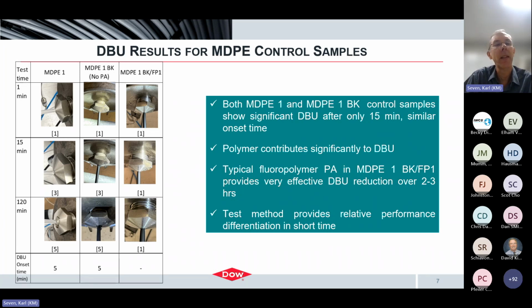MDPE1 BK, so that's the next series of pictures I show here. That is basically a fully formulated jacket compound, but with no processing aids. And so overall, the buildup is about equivalent to the first series of pictures, having an onset time of buildup of about 5 minutes. And so this basically is suggesting pretty much that the polymer is contributing significantly to the die buildup overall.